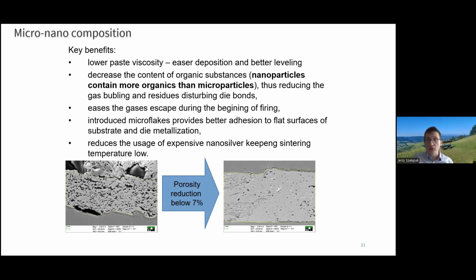To reduce the porosity even more, we used a method of decorating silver microparticles with silver nanoparticles. During sintering, the nanoparticles acted as a glass fluid, wetting the grain surface at the contact point, replacing the solid layers at the intergrain boundaries in the neck area. At the same time, the molten nanoparticles fill the pores that are formed, reducing the porosity of the layer. Replacing the electrically non-conductive glass fluid with conductive materials allowed for a lower electrical resistivity and higher thermal conductivity of the layers, while maintaining a low sintering temperature within 300 degrees, which is important in assembly. In turn, we reduced the amount of expensive nanoparticles.